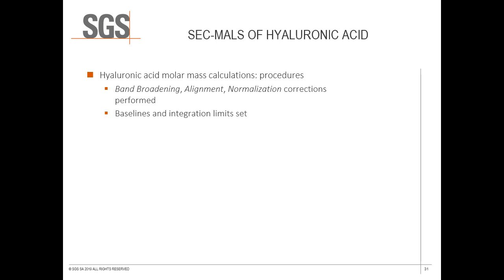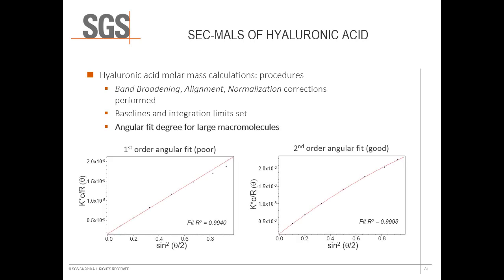An additional feature to consider when working with high molar mass samples is the Zimm plot fit degree. The default for this feature in Astra is a first-order fit. The angular dependence of the Zimm plot may become nonlinear, however, for very high molar mass samples. When analyzing samples expected to be over 1 million grams per mole, be sure to evaluate the validity of the default setting across the peak. It may be necessary to utilize a second-order fit.